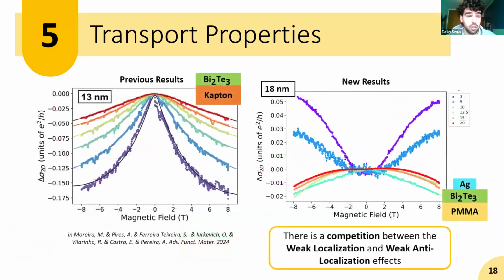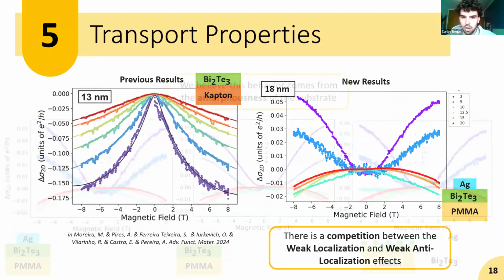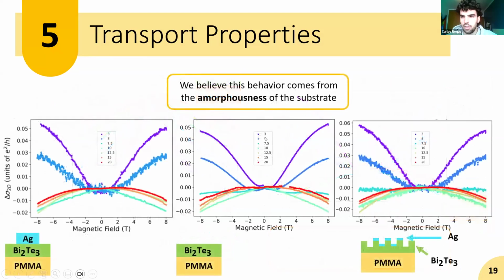Then we measured the magnetoconductance. We already did this in the research group with bismuth telluride and Kapton. We observed the emergence of the weak antilocalization effect, but with these new results, we observe a competition between the weak localization and the weak antilocalization effects. We find this a bit odd, so we tried to identify where this came from.